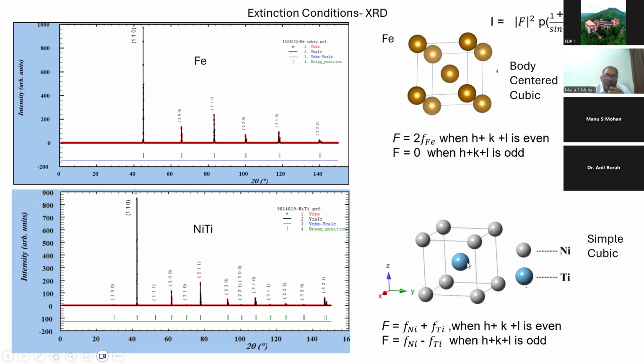Clear? So now when we go to NiTi, it appears to be again body-centered cubic, but there lies the point - it is not body-centered cubic, it is called simple cubic. You see here the corner atoms are nickel, whereas the body-centered atom is titanium. So if you substitute 0.5,0.5,0.5 and 0,0,0 in the expression for f, you get f equal to f_ni plus f_ti when h plus k plus L is even, and f equal to f_ni minus f_ti when h plus k plus L is odd. That is, it is no longer body-centered cubic, but it is simple cubic.